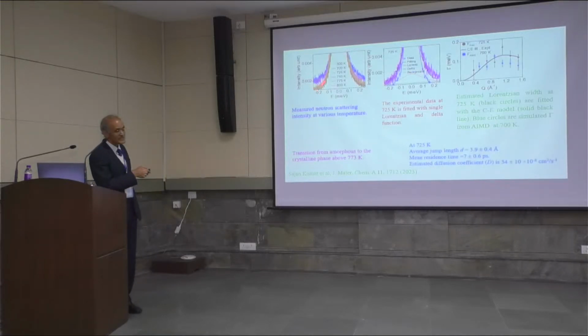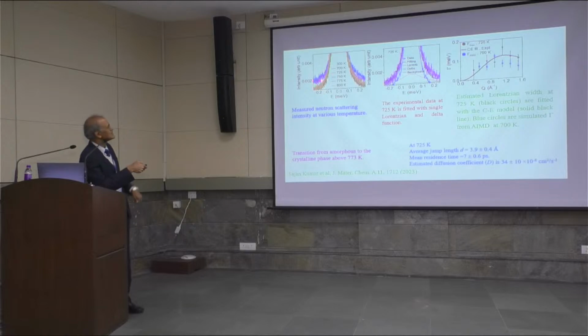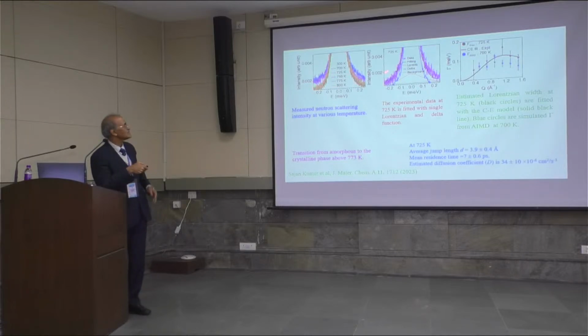Okay, this is data of the quasi-elastic neutron scattering. So for the elastic line, we have just shown the tail part of it. You can see that at low temperature you have essentially only the resolution of the instrument. As you increase the temperature, there is a broadening of the elastic line, and you have some increase in the intensity also because of phonons, but that can be accounted for. So this is fitted to a Lorentzian kind of function, and the width of this Lorentzian function is plotted as a function of the momentum transfer.